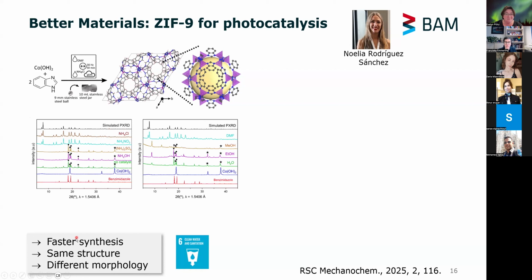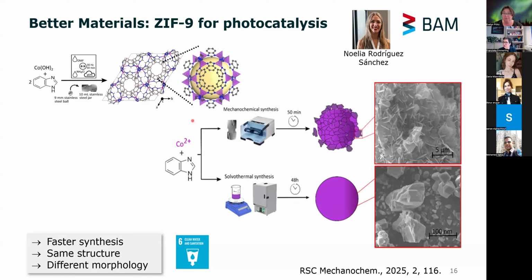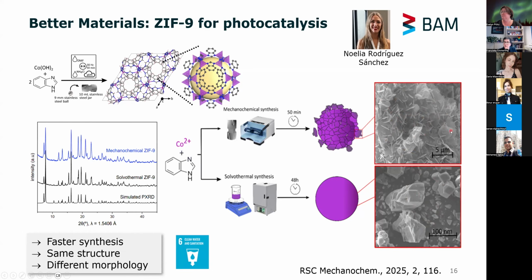But overall, it's a faster synthesis. We get the same structure as you get in solvothermal synthesis, and it takes just roughly an hour, whereas in the solvothermal way, it's a bit longer. If we look here at the resulting crystallites, you can see that these under mechanochemical conditions are more plate-like, and here you have more of a rod scenario. And this is maybe the main reason why they also perform better when we test them for photocatalysis. I will show in a second.